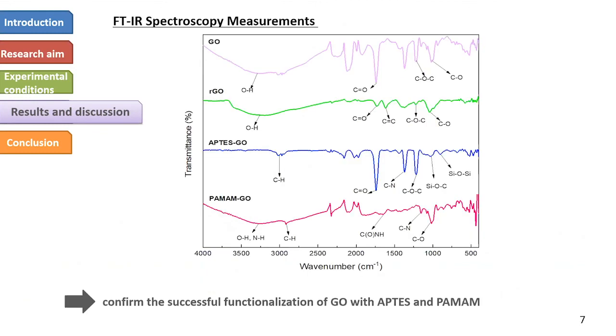In order to prove the modification of GO, FTIR spectra of GO, RGO, APTES GO, and PAMAM GO were examined. We can observe the signals representative for the oxidation groups found on the surface of GO, which are hydroxyl, carboxyl, and epoxide groups. And in the case of reduced graphene oxide, these signals are not so intense.